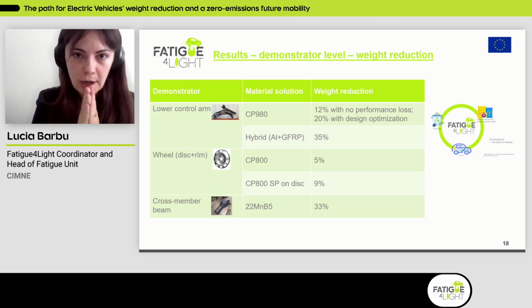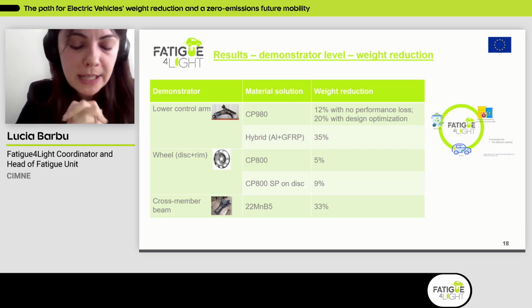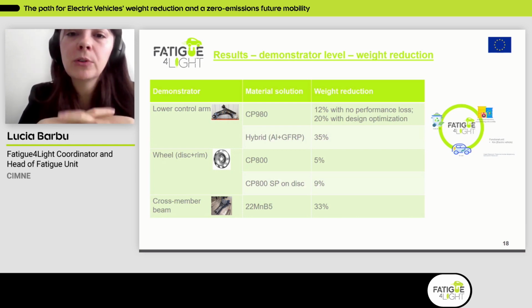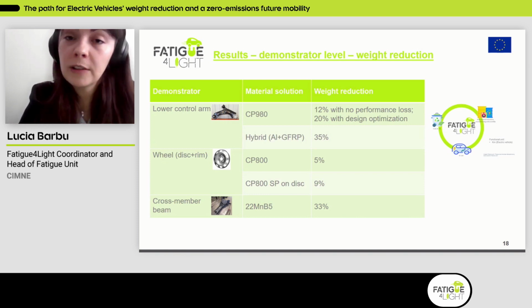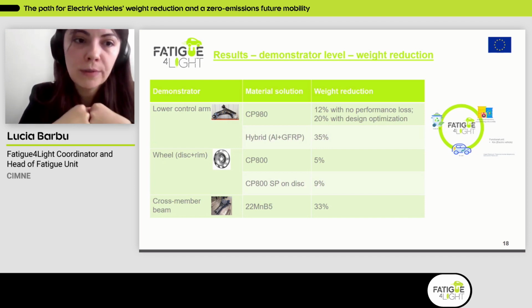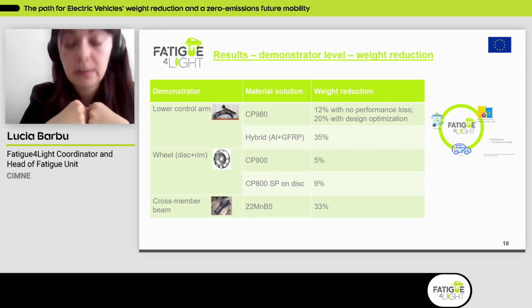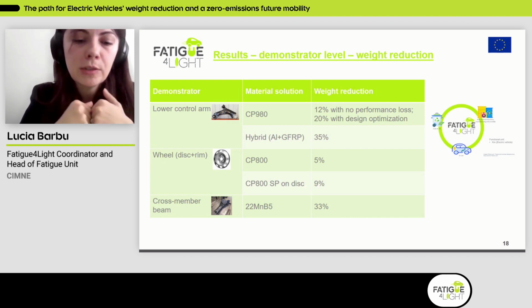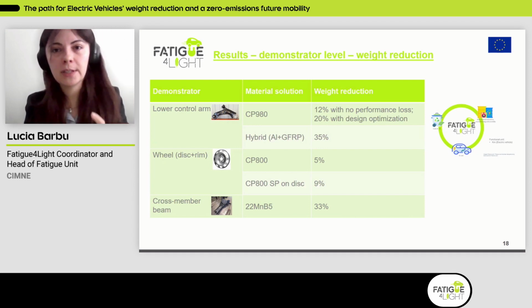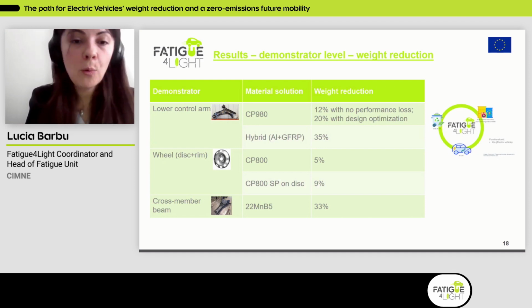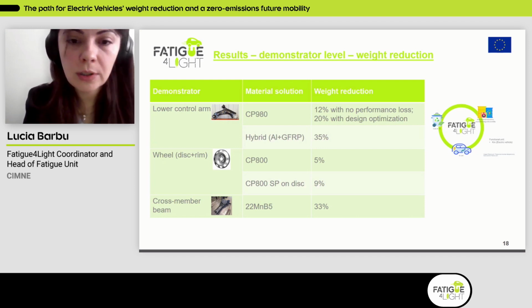So for the lower control arm, when we switched to the CP980, we observed that we were able to achieve a weight reduction of about 12% without any performance loss, 20% if we also incorporate design optimization. The hybrid solution for the lower control arm, of course, a high weight reduction, 35%. For the wheel, for the CP800 solution for the disc and the rim, 5% average weight reduction. When you also improve the performance of the material by using a shot peening process on the disc, you get a weight reduction of about 9%.